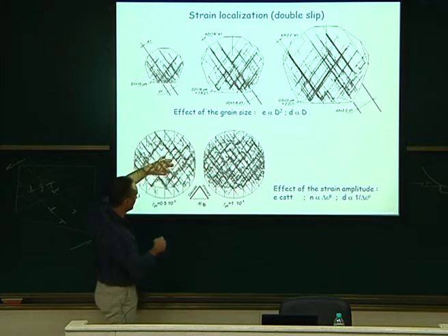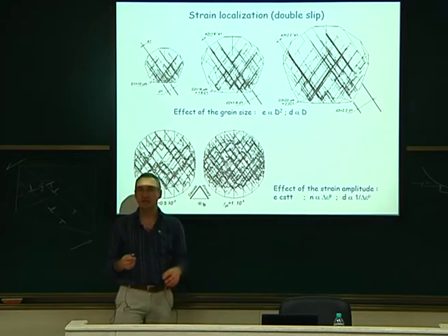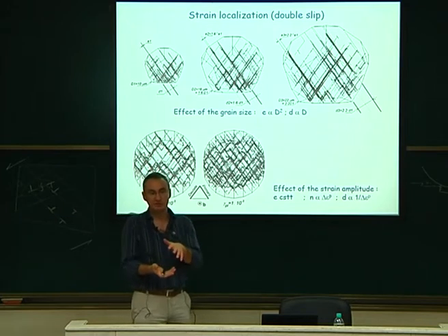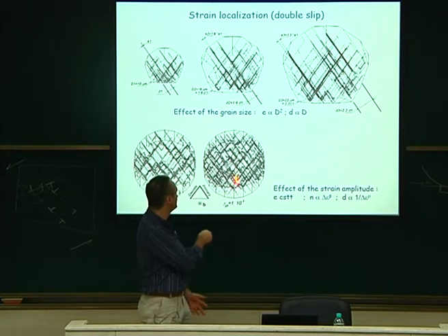It's comparable. Here I have doubled the plastic strain. The size is not doubled, but the number of bands is doubled. Here you have more bands than here. So it means that it's as if each band was able to accommodate a given amount of plasticity and not more. So if you need more plasticity, you need a new band. Okay, this is what we found here.